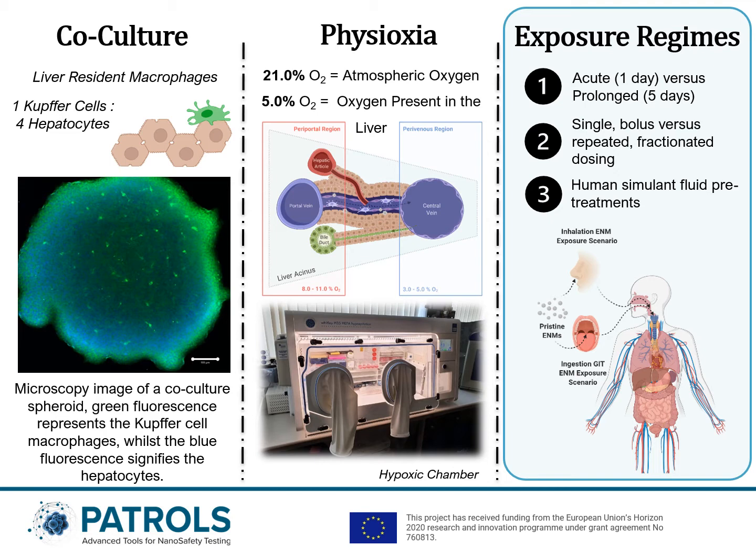It was also considered that the nanomaterials reaching the liver may have undergone biotransformation from contact with various biological fluids whilst translocating through the body prior to reaching the target organ. So this biotransformation can transform the properties of these materials, and so a tiered testing strategy and SOP for mimicking nanomaterial biotransformation in the liver were developed.